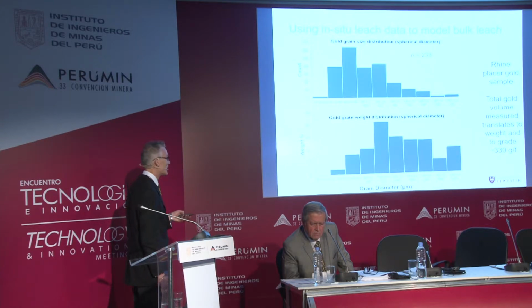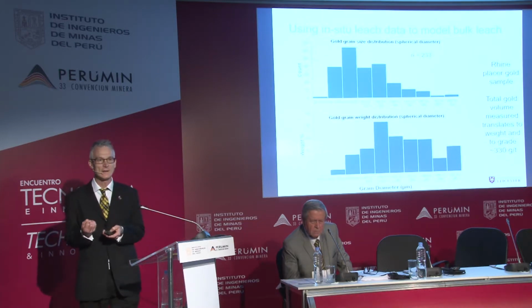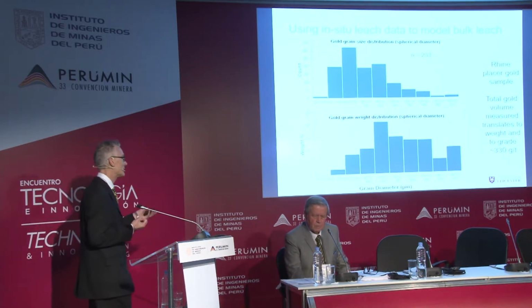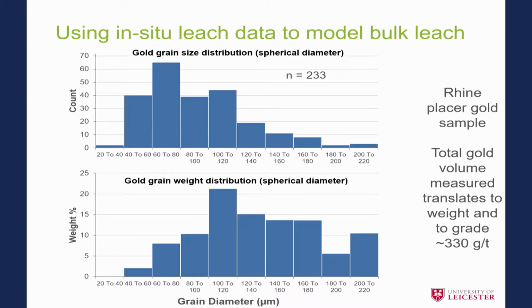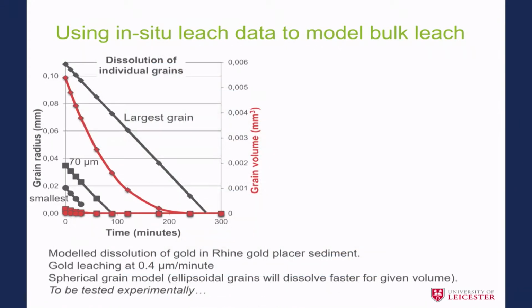Okay, we can add all that up and we can actually give an estimate of the total amount of gold in the sample, which in this case is around 330 grams per ton. And then we can model how these grains are going to dissolve. If we look at the left-hand axis, this is our largest grain at a linear rate of 4 microns in 10 minutes, or it will dissolve in this way, and that's our smallest grain. The volume obviously is related to the cube of the radius, so it actually goes down much faster if you look at the right-hand axis.